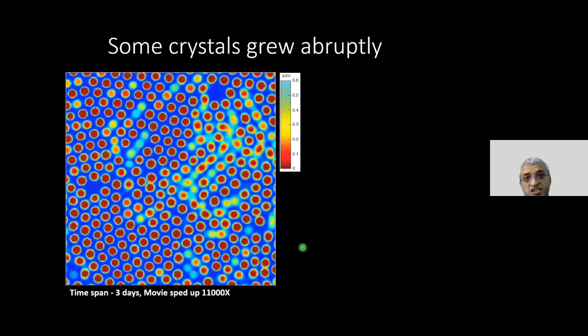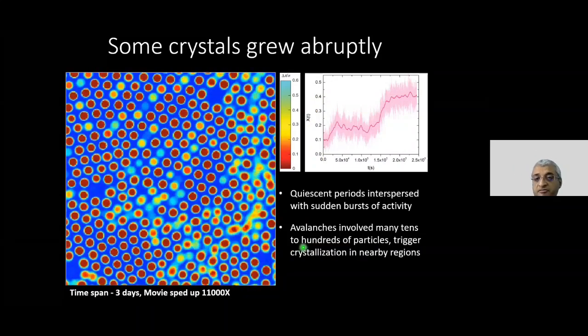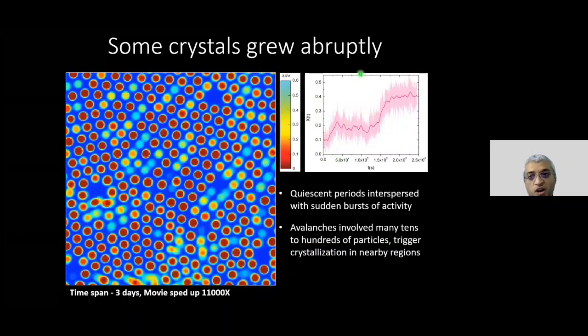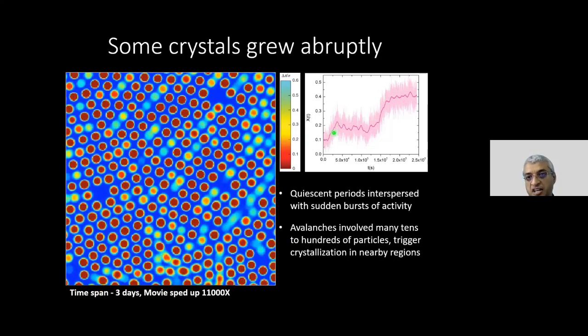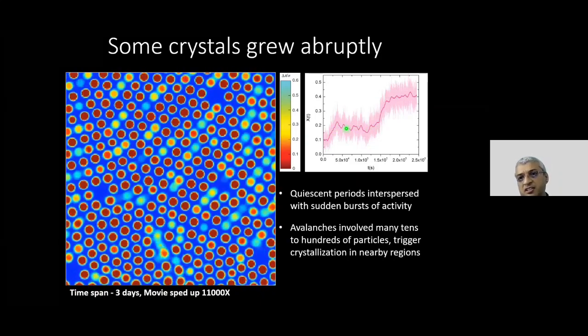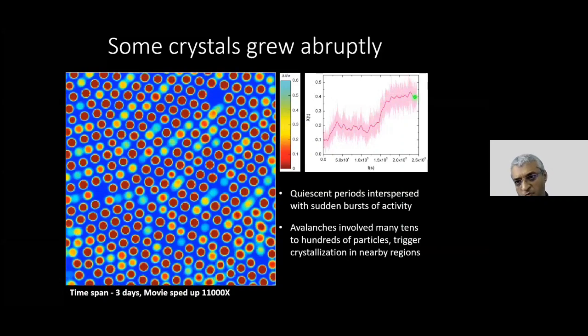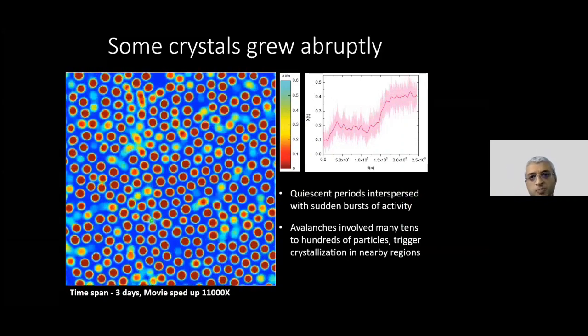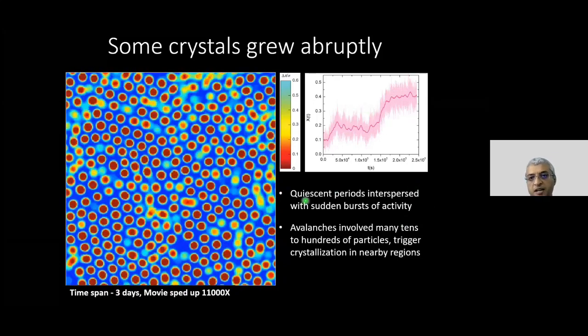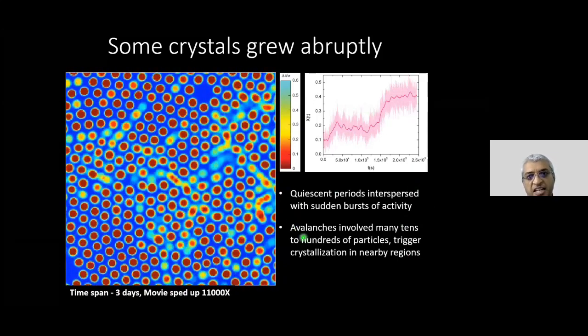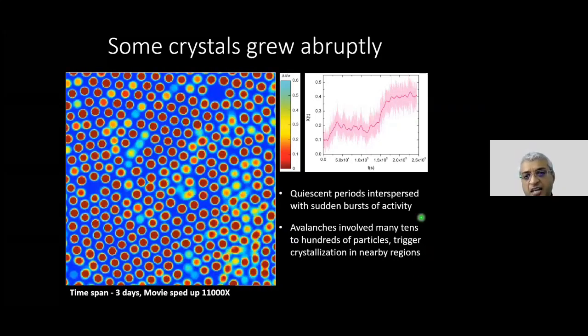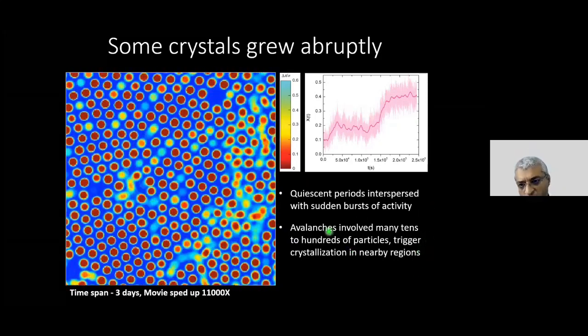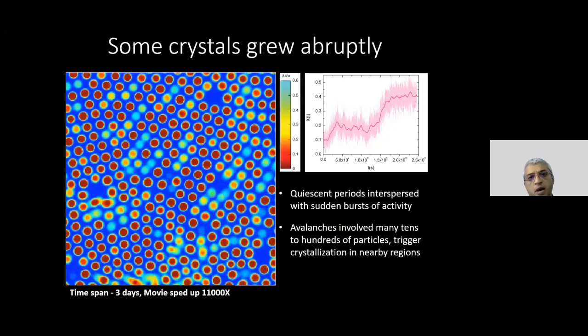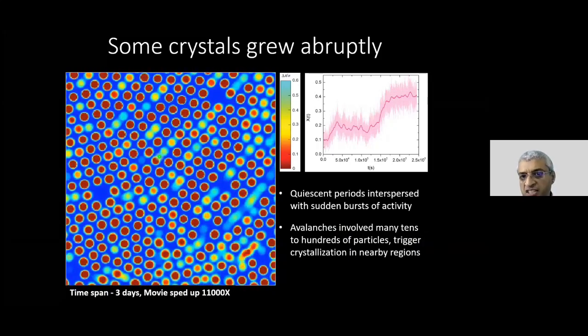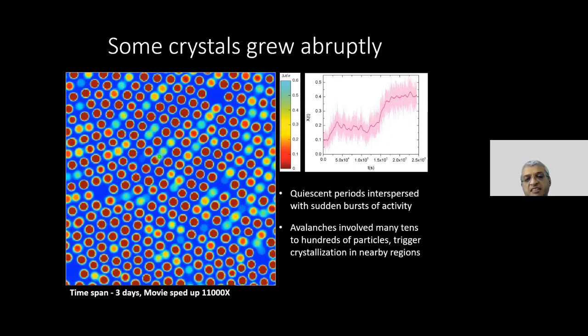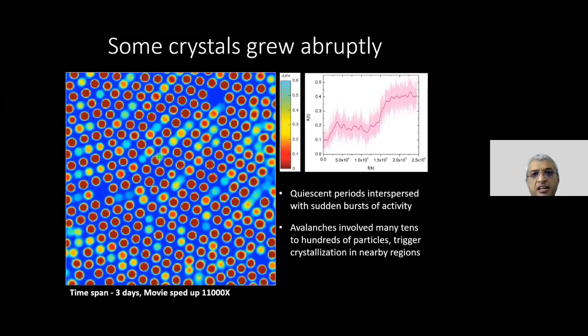Okay, so for this crystallite, if I were to track what's going on as a function of time, what I see is not what I saw earlier. I basically see an increase in crystallinity, a long plateau in which nothing changes, then an abrupt increase in crystallinity followed by a plateau again. So this process is very different from what I showed you earlier. And this sudden burst in activity is what I'm going to call an avalanche. And avalanches involve many tens of particles, and also the particles that participated in an avalanche are not the ones that crystallize. So basically, I see the spurt of activity and crystallization gets triggered in neighboring regions.